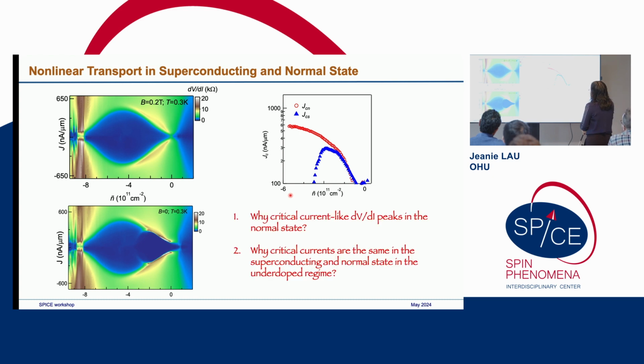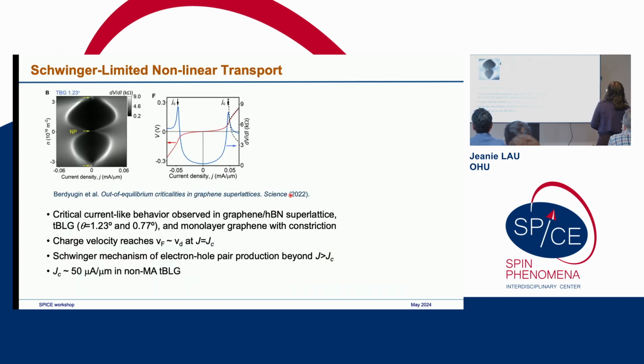Okay, so now this is actually really strange. What's strange is, why do we have critical current, dV/dI peaks, in the normal state? So that's the first question. The second question is why are the critical currents the same in the superconducting and the normal state? And this is in the underdoped region. In the overdoped region, they actually bifurcate, right? So they become different.